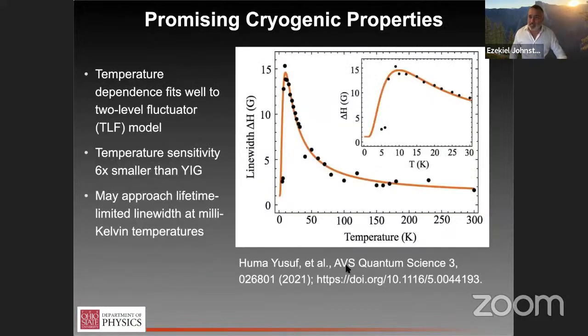And this is the last slide, and then I'll open it up for questions. The other key parameter, of course, as a function of temperature is the line width. And you can see that the line width actually gets worse as the temperature goes down, which might be initially counterintuitive, but then comes back down to recover the room temperature value below about 10 Kelvin, as you can see in this inset. So this orange curve isn't just a guide to the eye. This is actually a theoretical calculation.